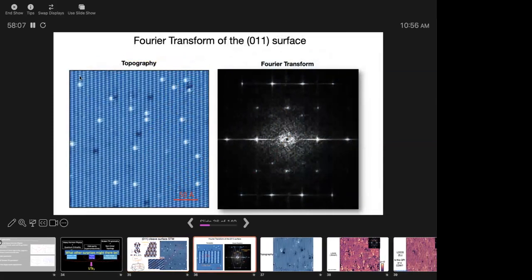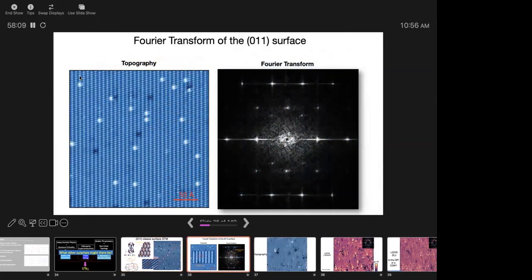Okay, so now if you take this topography and do a Fourier transform, these are the tellurium peaks, Bragg peaks in the Fourier transform. 1, 2, 3, 4, 5, 6. The way to think about the surface is like it's a squished hexagon. That's the best way to think about the surface. So it's squished in this direction.